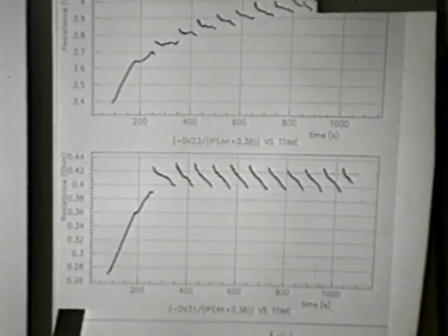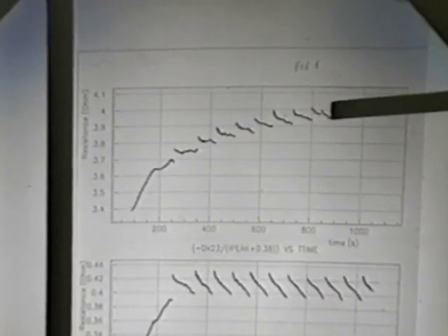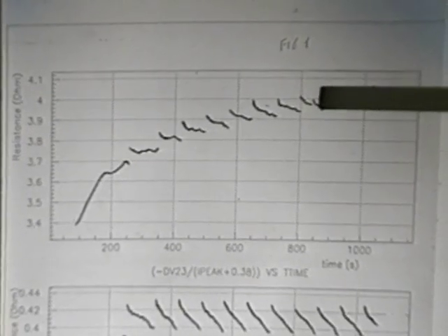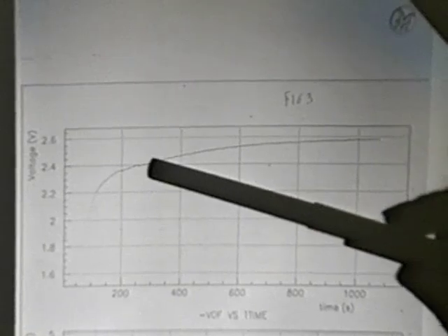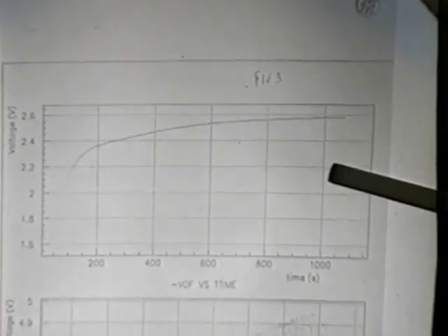This point is very important because it is the wire of palladium without a counter electrode, and even so the wire gets the intrinsic jump, not related, after 800 seconds. So this is the proof that the electromigration effect is effective. This is the voltage between anode and cathode starting from the zero time. These jumps, these flats correspond to 0.6, 0.8, and so on. Very reproducible. And the mean value corresponds to the bulk effect of loading.